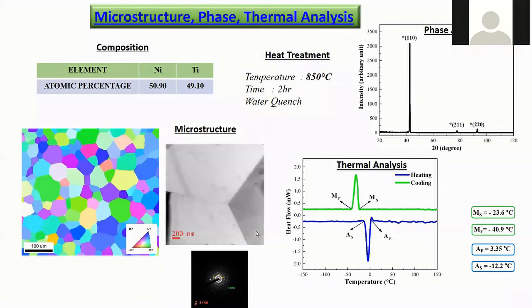So what we intend to do is to find out the pseudoelastic property of each of these grains with different orientation. Now, each of these grains is an austenite one at room temperature, right? These austenite grains have the same crystal structure, but are oriented along different directions, as you can see, this color signifies that. So when we are talking about the transformation from austenite to martensite, it is not necessary that all the grains will deform at the same starting martensite transformation stress.